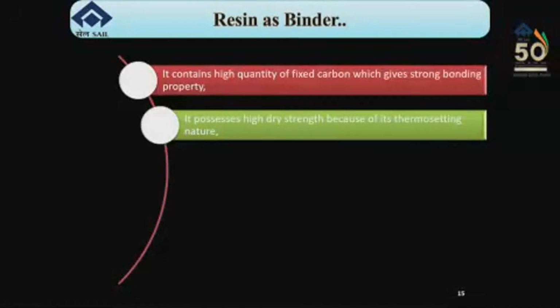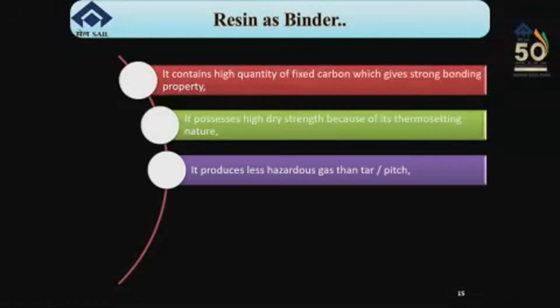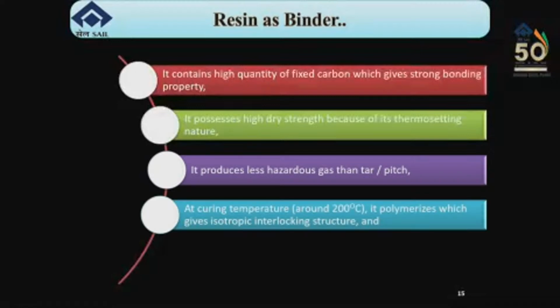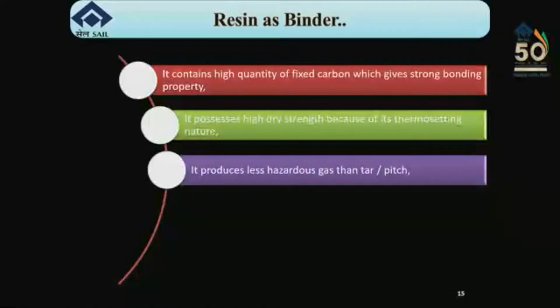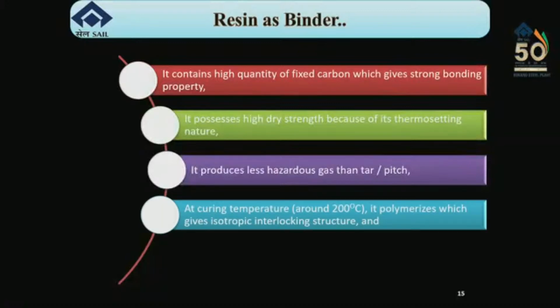Resin is used for its high quantity of fixed carbon, which gives strong bonding property. It possesses high dry strength because of its thermosetting nature. It produces less hazardous gases than tar and pitch. At curing temperature around 200 degrees Celsius, it polymerizes, which gives isotropic interlocking structure, and cold crushing strength, that is CCS, increases with the increase of resin content.